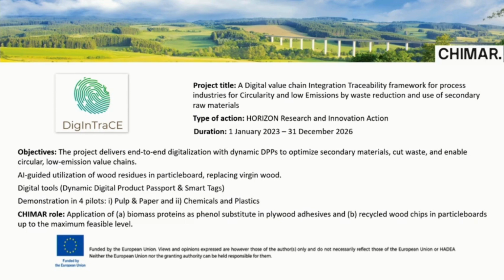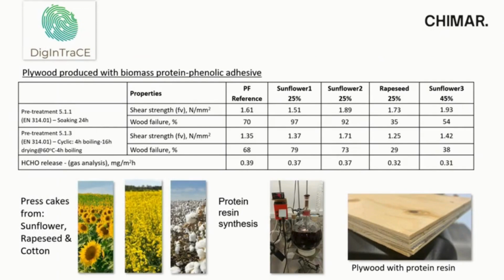Our role here is to use some biomass proteins as phenol substitute for plywood boards, and also to use recycled wood chips in particle board production. Here are some results where we have used proteins from sunflower and rapeseed. We produced the resins with various substitution levels, and then we continued with the plywood production. As you can see, in most cases, we have better shear strength values than the reference resins and quite good wood failure values.